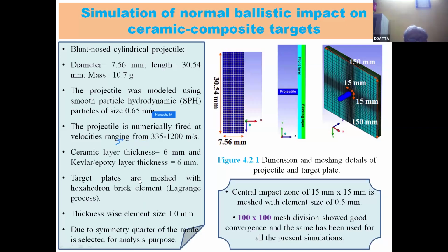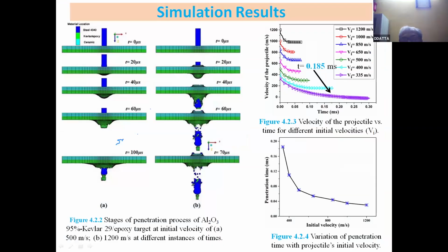Thickness-wise element size is 1 millimeter, but in plane mesh size is reduced, particularly at the zone of interest. Now here you can see the simulation results at different times. This is the beginning, at 0 microsecond. At 20, you can see the bulge. At 40, the bulge has increased. Then here the shear plug is visible at 60 microsecond. At 100 microsecond, the projectile has come out together with a shear plug. This is for a low impact velocity, yes, it is 500 meter per second. This is part A. So here you can see the damage is moderate.